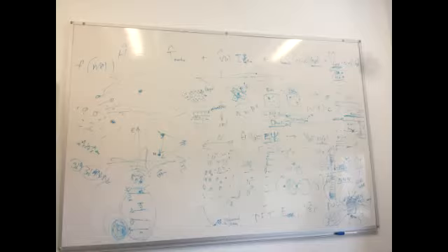The density is sometimes useful, especially, so again, you have your states, and you can look at every state here. As we said, let's say we have this state here, and you can draw a wave function which corresponds to this state. Most likely it will just sit over the entire crystal. But if you have some defect inside the crystal, you will look at the density or wave function of this state, and you will see that it sits exactly on this defect.